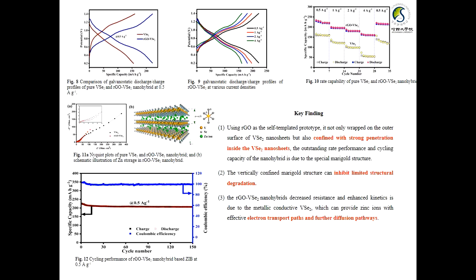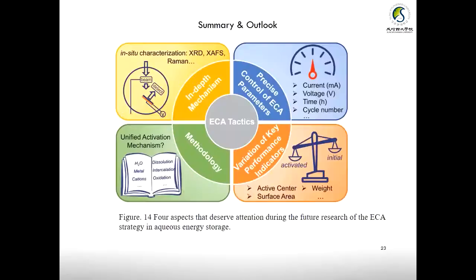The key findings which I noted is that the reduced graphene oxide used as a template is not only wrapped on the outer surface but also confined with a stronger penetration inside the VSe2 nanosheet. The outstanding rate performance and cycling capacity of the nanohybrid is due to the special marigold structure. The vertically confined marigold structure can inhibit structural degradation. The RGO VSe2 nanohybrid's decreased resistance and enhanced kinetics is due to the metallic conductivity of VSe2, which further provides zinc ions an effective electron transport path and diffusion pathway.